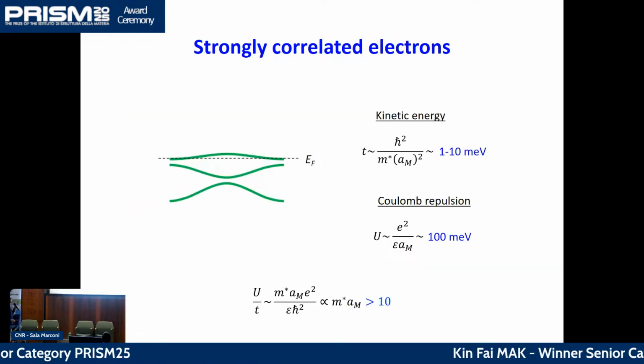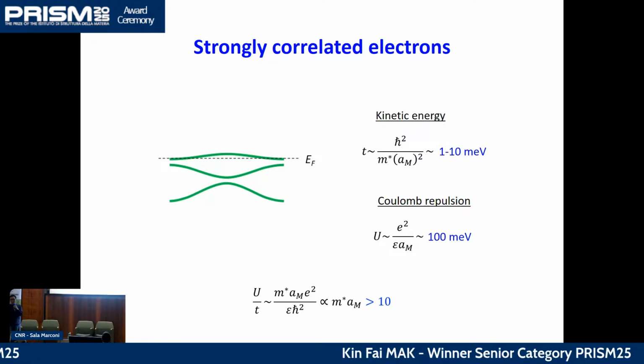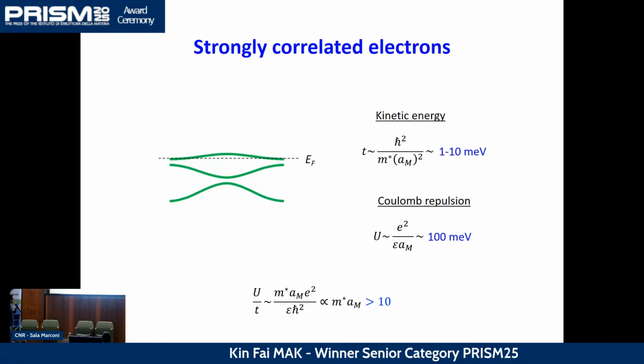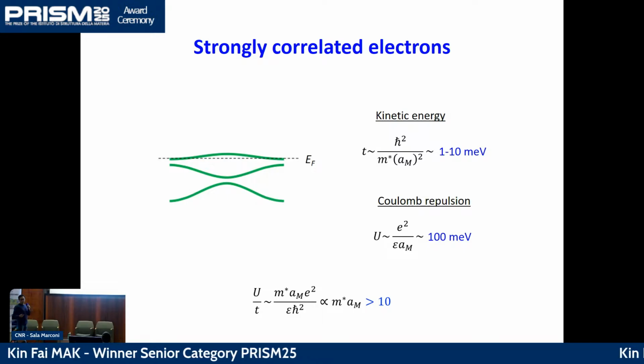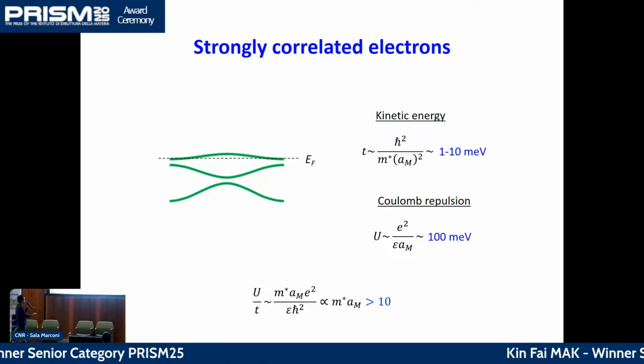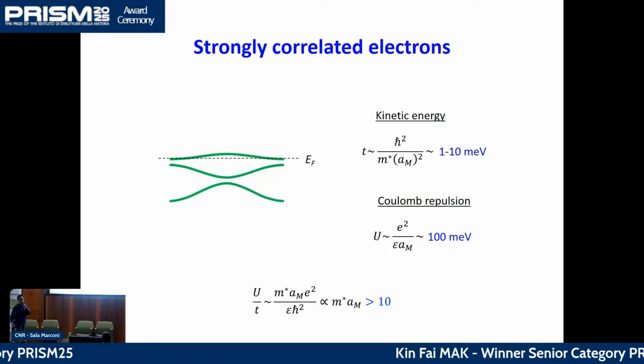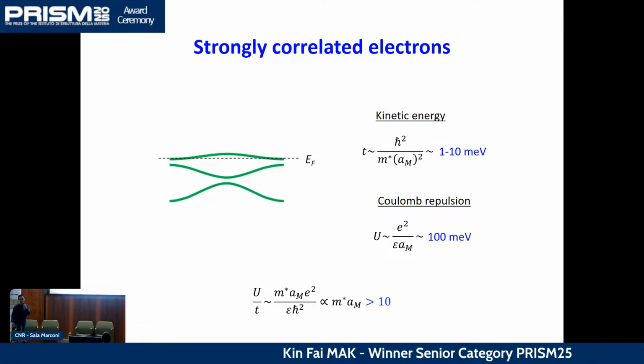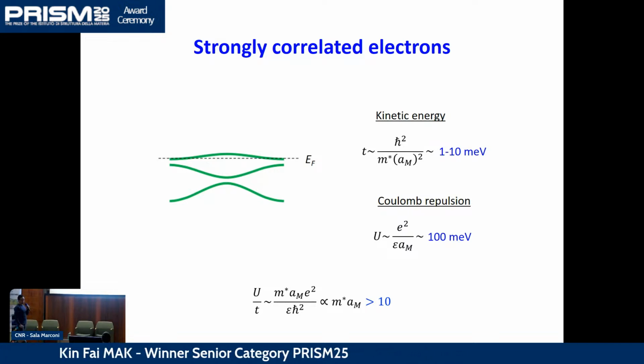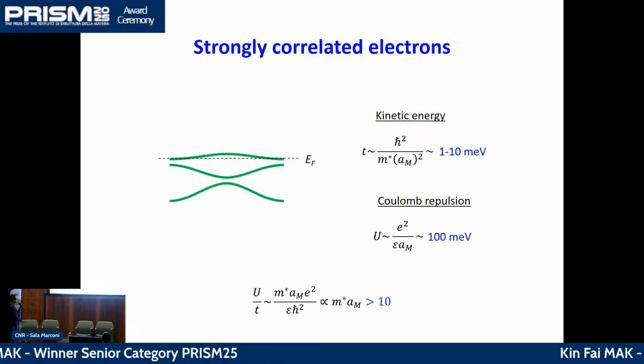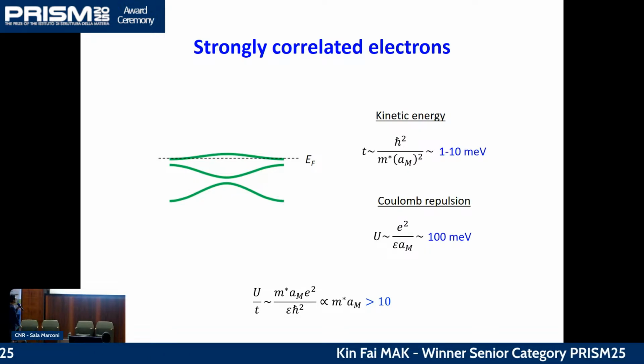And finally, I want to say that the electrons are intrinsically strongly correlated. Let me explain what we mean. The electrons have kinetic energy of this form here. The kinetic energy of a non-relativistic electron is proportional to the momentum squared, and as a result, the momentum is proportional to 1 over the moire length scale, so the kinetic energy goes as 1 over the moire length scale squared. Okay, and typically we are talking about 1 to 10 milli electron volt kinetic energy, which you can think of as basically the width of this band.